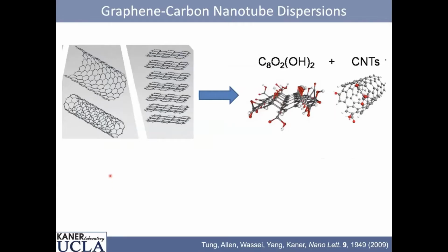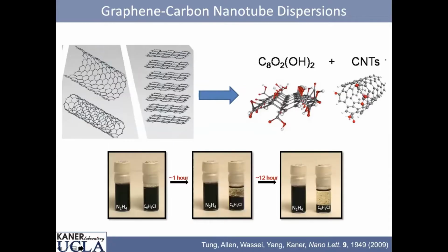Now, another thing we can do with graphene is we can combine it with carbon nanotubes. And so we did this. This is with my colleague Yang, who's an expert on things like memory devices and optical devices. And what we wanted to see is what happens if we put this in hydrazine as opposed to chlorobenzene. Chlorobenzene is a pretty good solvent for carbon nanotubes. But you'll notice that after 1 hour, everything's still stable in pure hydrazine, but it starts coming out of chlorobenzene. And in fact, here's 12 hours, but this is stable for months or probably years.